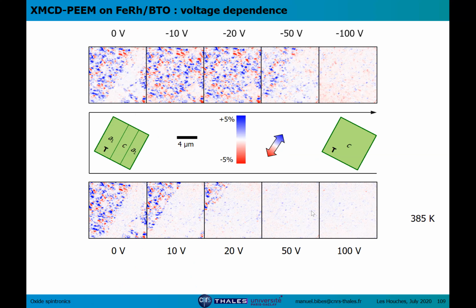This is another way to visualize this effect using XMCD-PEEM at the iron L edge at 380K, I think 385K. You see that depending on the voltage that is applied, we are able to go from an antiferromagnetic state, where we have almost no signal, to a ferromagnetic state where we have this large red and blue contrast, which correspond to ferromagnetic domains in the ferromagnetic state.